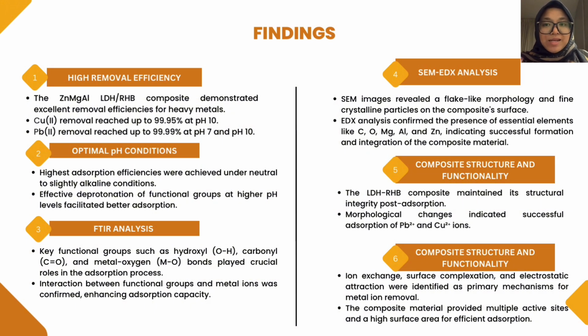Through SEM EDX analysis, I observed a flake-like morphology and fine crystalline particles on the surface of the composite. This indicates a high surface area, which is beneficial for adsorption. EDX analysis further confirmed the presence of essential elements like carbon, oxygen, magnesium, aluminium, and zinc, which show the successful formation and integration of the composite material.